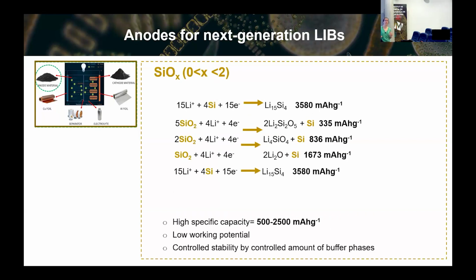And this is the use of SiOx. So SiOx essentially is like having a composite in which we have at the nanoscale some silicon and some SiO2, some silica, mixed together. So the silicon on the first cycle will lithiate to lithium silicide, and the silica will convert to silicates plus silicon. So if we tailor the oxygen content, the silicon to silica ratio, then we might be able to tailor the amount of buffer phases.